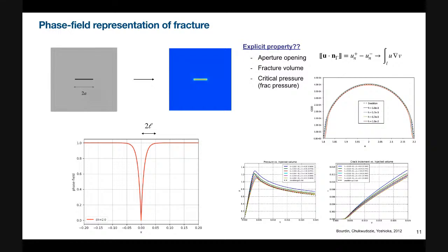And we verify this fracture aperture computation against the closed form solution. The vertical axis is the fracture aperture, and the x-axis is the distance along the crack. This dashed line is the analytical, closed form solution from Sneddon. And then we computed the fracture aperture with different mesh sizes. These different colored lines represent results from different mesh sizes. Notice here that our fracture aperture is on the order of E minus 4. And we are able to recover this fracture aperture using even a mesh on the order of E minus 2.